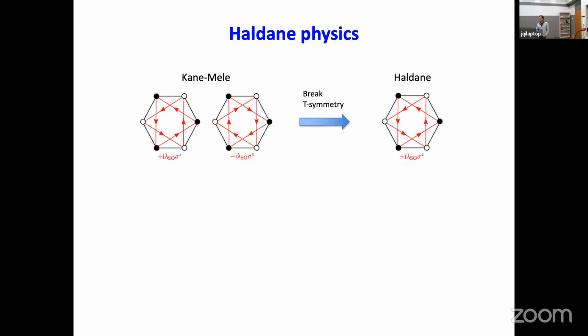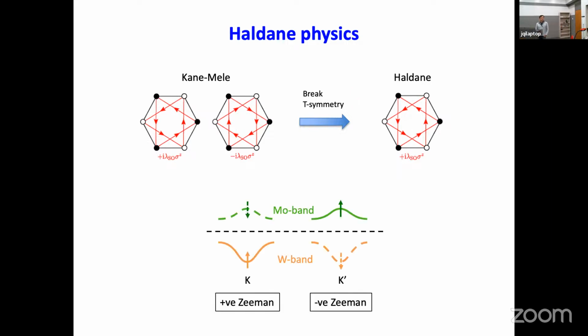So that's the idea: by just breaking the symmetry, we split the 2 copies of the Haldane and retain just 1 copy left in the system. And it turns out that the band structure of this particular A-B stacking of material is just ideal for doing that. So here is the band structure of the A-B stacking. What's so unusual about this is that if you look at the Mo-band, which is the green band here, from the K and the K prime valley, the spin and the valley are locked because of the large spin-orbit interaction in the material.